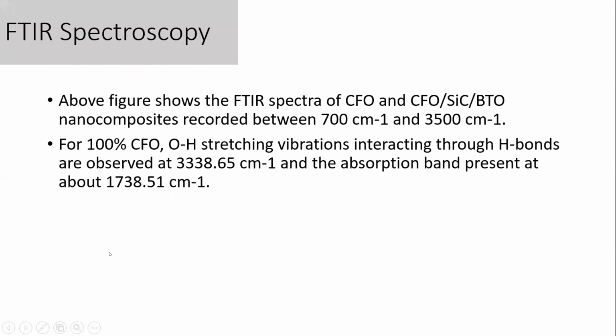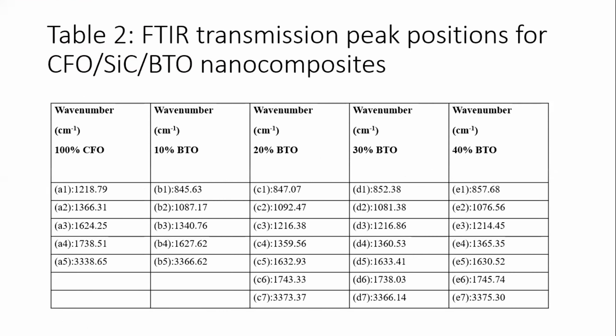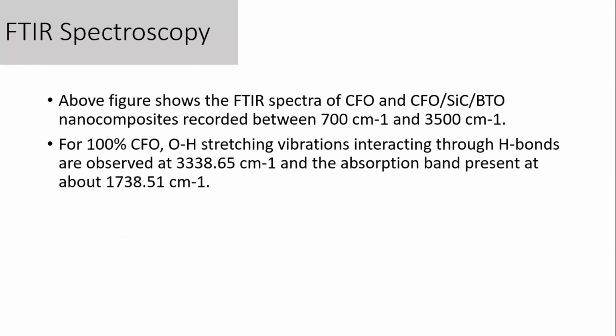3338.65 peak tells us about the OH stretching vibrations interacting through H bonds. And this was observed, and we have also tried to take help of some research papers in order to validate whether the peak positions that we are getting are analogous to their data or not. And we found out that the peaks were very near to this range, 3338.65 per centimeter. And the absorption band was found at 1738.51 per centimeter. Now, the further analysis of this nanocomposite series is under progress.